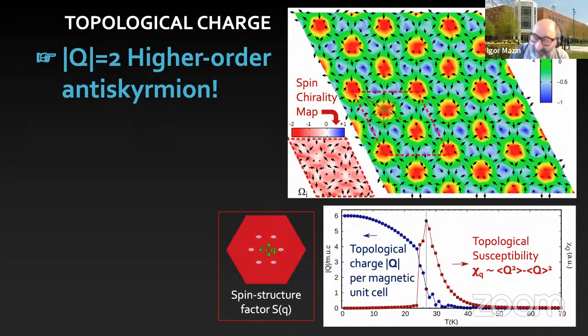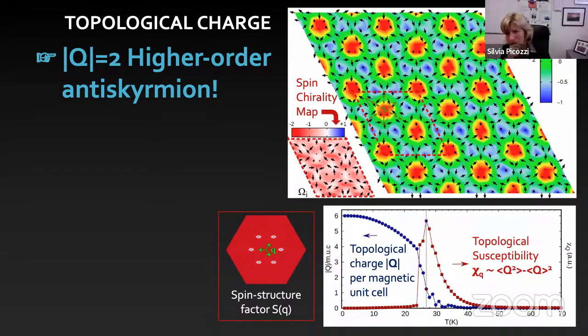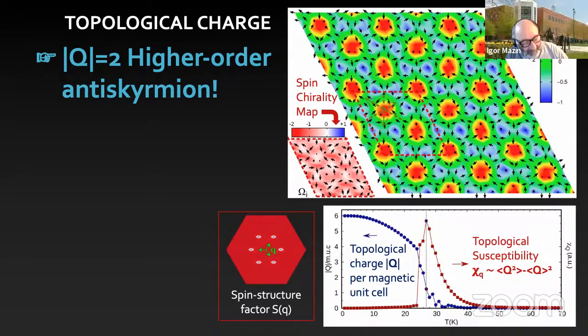Hi. Thanks, Silvia. Interesting talk, brings many thoughts. I don't want to be very controversial, but I think you have a tendency to make general statements in cases when the statement is applicable only for a particular case you are discussing. For instance, there are van der Waals materials where TC actually increases with a small number of layers compared to the bulk. Chromium sulfur bromide (CrSBr), the large J3 is extremely ubiquitous for all triangular materials, and usually does not come from ligand-ligand interaction, but from T2g-eg hopping, and so on.